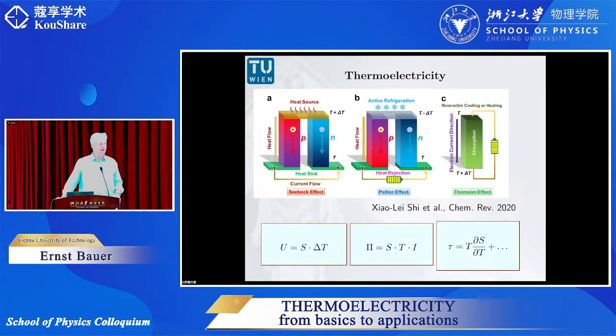And if you increase a little bit the temperature on the hot side, then more of the hot electrons will flow to the cold side. But on the same step, the electrical field will increase a little bit more. And from these statements, one can say that the voltage which is created is proportional to the temperature difference. And the proportionality constant is the so-called Seebeck coefficient, or frequently also termed thermopower.